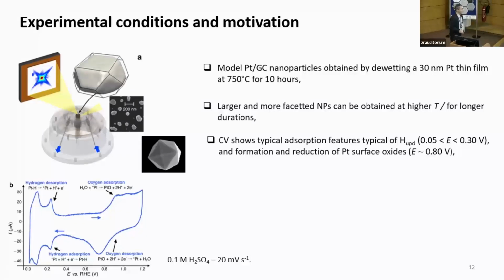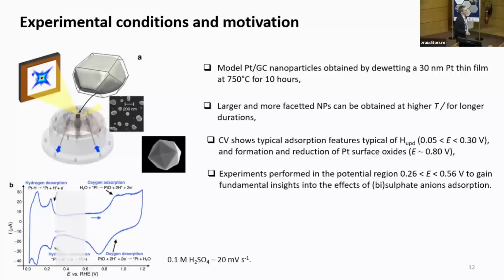CV is a state of the art, so you have seen a lot this morning, so you are becoming expert in platinum electrochemistry. So we have this adsorption desorption feature of platinum, oxygen adsorption desorption features. And what we were interested in was this potential region where essentially the cyclic voltammogram is kind of flat. There is not so much variation in current in this region as a function of the electrode potential. And as I've already mentioned, this is the region into which you start to make the electrode surface a little bit more positive, and you start to attract the anion to the surface.